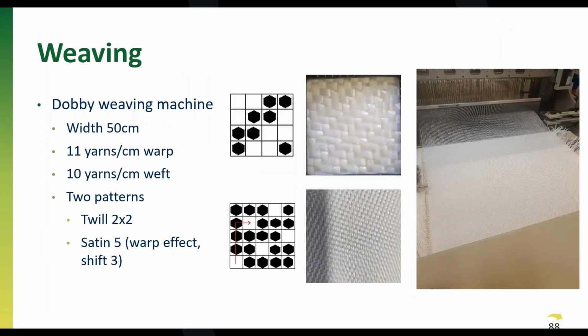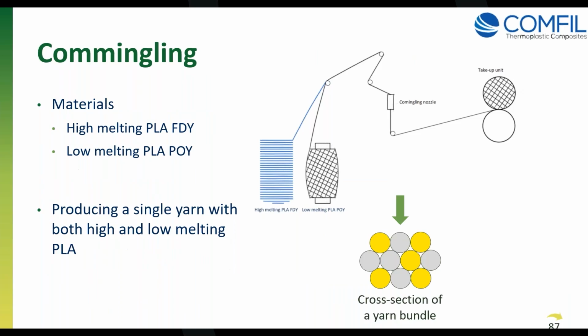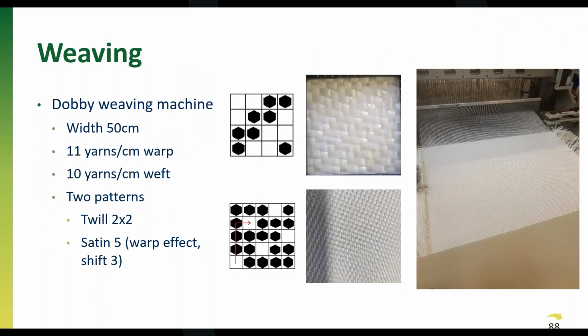With that yarn, we also went to the weaving machine, a Dobby weaving machine with a width of 50 centimeters. I forgot to mention, this commingling here is also done by Comfil, by Hans, who will be speaking a little bit later. For the weaving, so 11 yarns in warp, 10 yarns in weft per centimeter, and we tested 2 different patterns, because for a composite material, it's very important that the yarn is stretched and does not have a lot of curves or bends, and that's also in the direction of the load that the composite is enduring. A Twill 2x2 and a Satin 5.